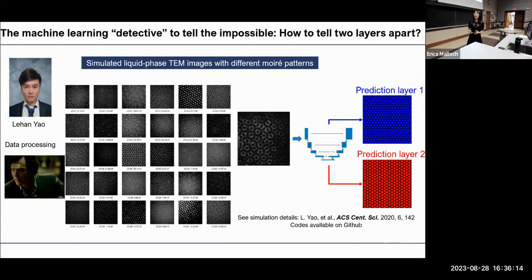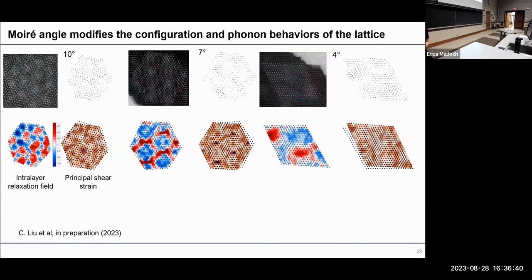He generated a simulated library of liquid phase TEM images of moire patterns shown here, and feed that into the training data set for a neural network because they have very well-established ground truths. And then after training, now the neural network can use an input as a raw data liquid phase TEM image of moire pattern to output the individual particle locations. And then with this single particle location tracking, now we can actually map out what is the displacement vector field.